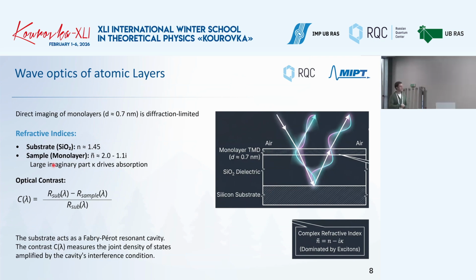So the substrate has specific n values, then the monolayer has its own complex refractive index. Then you can evaluate the optical contrast depending on the substrate and the sample. And it turns out that the substrate acts as a resonant cavity. So depending on these values, you either can see your material or cannot with a bare eye.